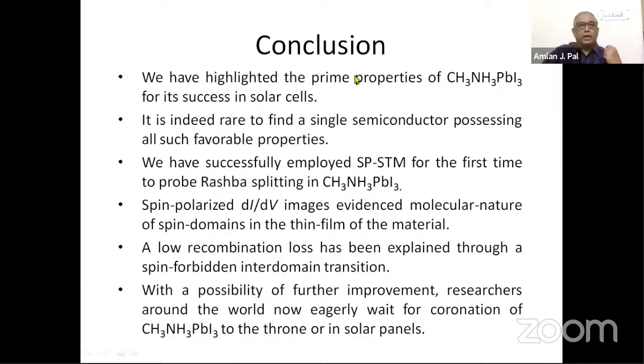So I now conclude that we have highlighted the prime properties of methylammonium lead iodide for its success in solar cells. It is indeed rare to find a single semiconductor possessing all such favorable properties. I listed so many properties, and you will find that it is really rare. We have successfully employed spin-polarized scanning tunneling microscopy for the first time to probe Rashba band splitting in methylammonium lead iodide, because this Rashba band splitting gives rise to low recombination loss. And this low recombination loss was considered to be very important for solar cell applications. As I said here, the low recombination loss has been explained through a spin forbidden inter-domain transition model.